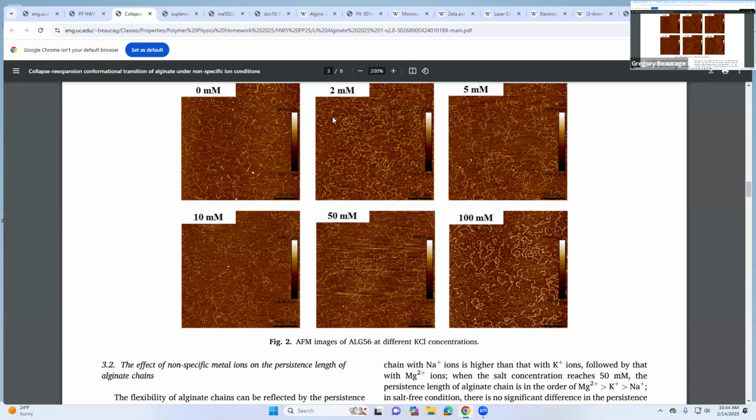Anyway, so it doesn't look dilute. That's the problem with this too. And also, if it doesn't look dilute, it means he's washing it. What he does is he washes across that mica that's been treated with the amines, and then he washes it a little bit and then he stops. He does it the same every time. But this is almost like a selection process. The ones that are more charged are definitely going to stick more, and the ones that are less charged are going away.